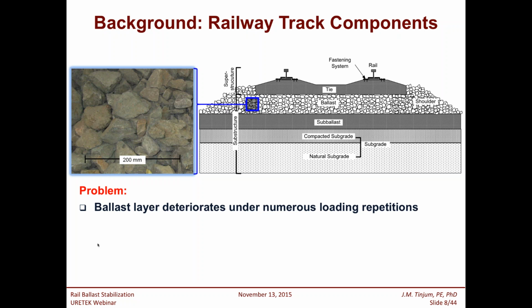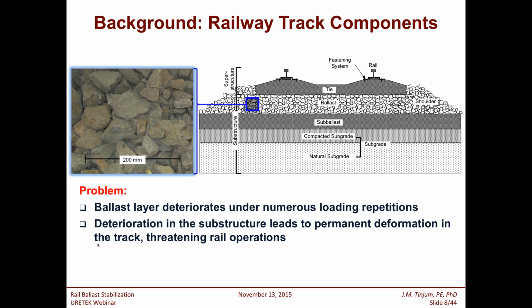So a problem statement is that this ballast layer deteriorates under numerous loading repetitions. This deterioration in the substructure leads to eventually permanent deformation in the track. That permanent deformation is what we call plastic strain, or the permanent accumulation of strain due to that loading. With enough plastic deformation, the geometry may be compromised, and we threaten the rail operations at a minimum. Often there will be speed limits posted to rail sections that have geometry issues where we just have to run the trains much slower than operations would like. And worst case situation, derailments that unfortunately we've seen time and again in the news over the past years.